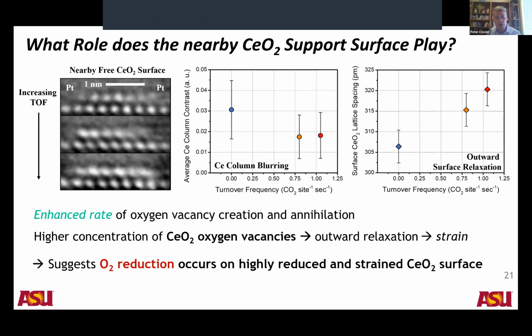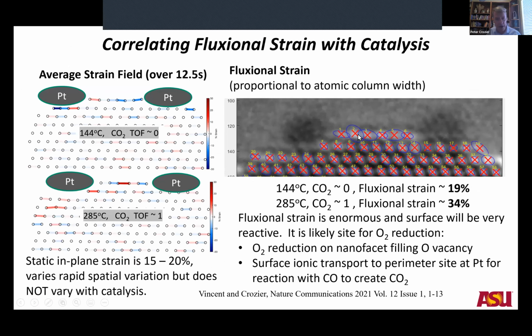And the creation and annihilation of oxygen vacancies, which is associated with this so-called Mars-van Krevelen mechanism of CO oxidation, is what's leading to the streaking of the top layer of cations on the surface here. And if you measure what we call the fluxional strain, it's approximately 34%, which is very, very large. And so the oxygen reduction reaction for the CO oxidation is actually taking place on these highly distorted and highly active ceria nanofacets located between the two platinum particles, and then the oxygen is being transported to the interface for the CO oxidation. So if you're interested in more of the details of this, we published this last year in this paper in Nature Communications.